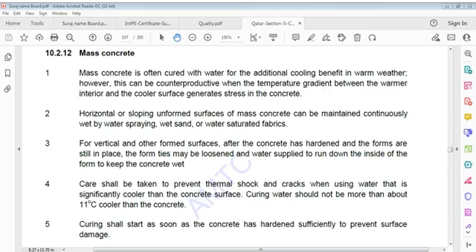Horizontal or sloping unformed surfaces of mass concrete can be maintained continuously wet by water spraying, wet sand or water saturated fabrics. For vertical and other formed surfaces, after concrete is hardened and forms are still in place, form ties may be loosened and water supplied to run down inside of the form to keep concrete wet. Again, the same care shall be taken to prevent thermal shock and cracks when using water that is significantly cooler than the concrete surface. Curing water should not be more than about 11 degrees cooler than concrete. Curing shall start as soon as concrete has hardened sufficiently to prevent surface damage.